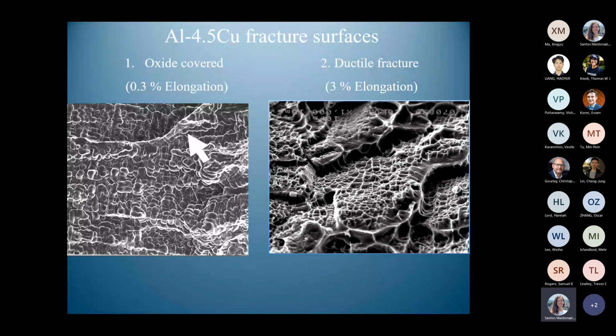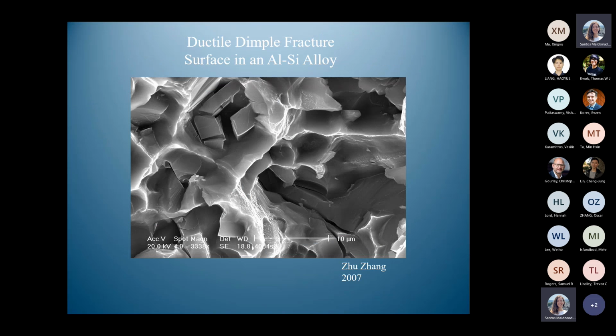Anyway, I was saying at the bottom of each one of these ductile dimples, there's a fractured silicon particle. And let's look at the next slide. Yes, here we are. Here's our fractured silicon particles, and here is the ductile matrix. And what you can see is the matrix is perfectly ductile because it's necked down to zero thickness. These knife edge arêtes are pretty well truly knife edge, which means that if we'd got a truly ductile material